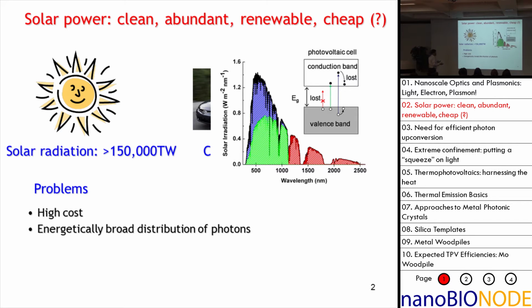Of course, there are other problems. The mismatch of the energy of the incident photon and the band gap of the silicon photocell. So right here at 1.1 electron volt, we are going to get very efficient conversion, at least thermodynamically, in that every single photon that falls in has exactly the right energy required to create the electron-hole pair. We'll get high conversion efficiency.